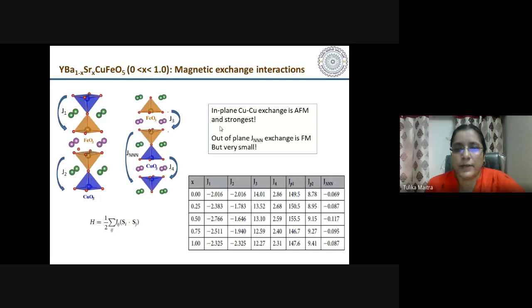So what we find is that this in-plane copper-copper exchange interaction is antiferromagnetic, and it's the strongest interaction, whereas the next nearest neighbor interaction, which is as shown here between iron and copper, is found to be ferromagnetic in nature, but it's very small. So this ferromagnetic nature can cause frustration to this commensurate magnetic state and lead to a spiral state, but the strength we see is very, very weak here. It's too small to cause sufficient frustration to give us a spiral state. Okay, so these are the observations that we can make, and we can see how the different exchange interactions compare with each other.